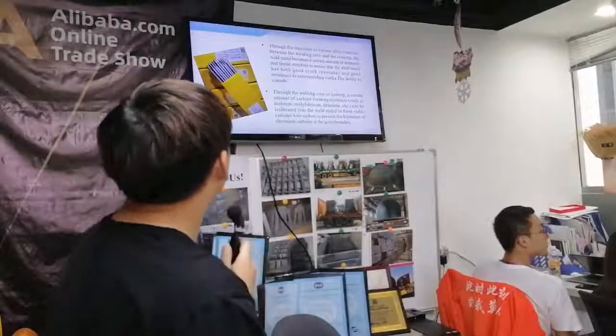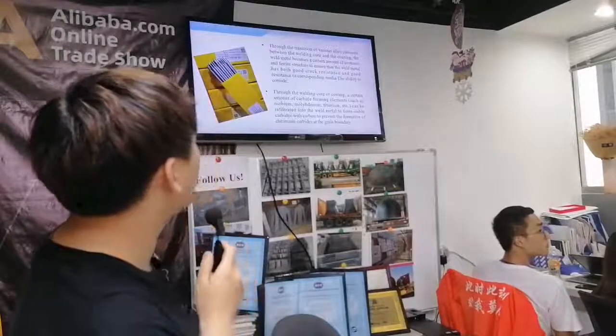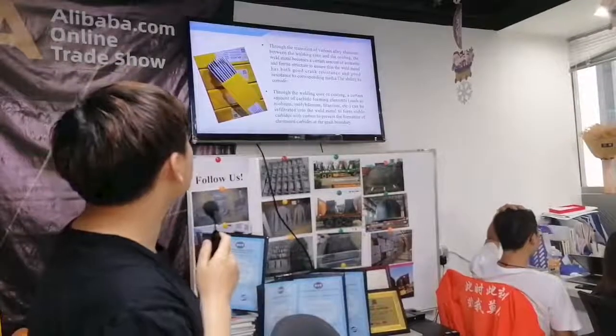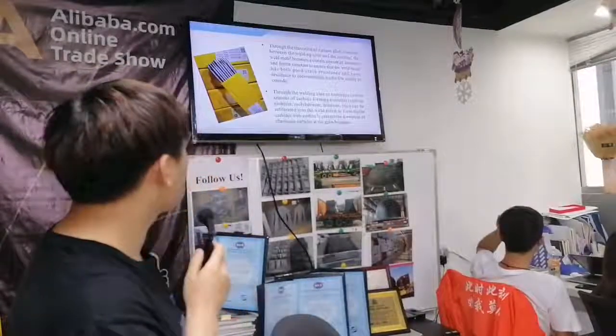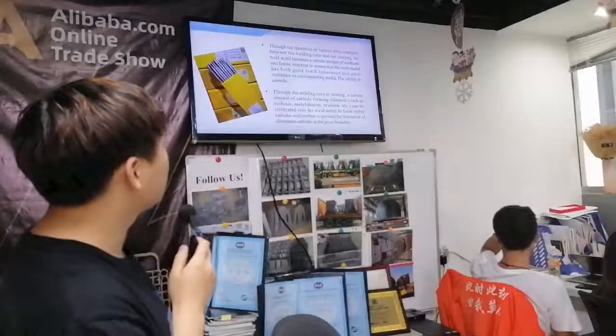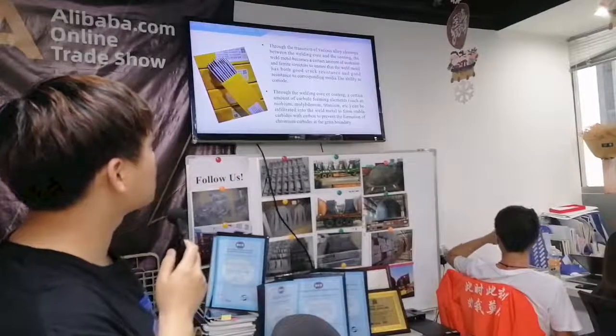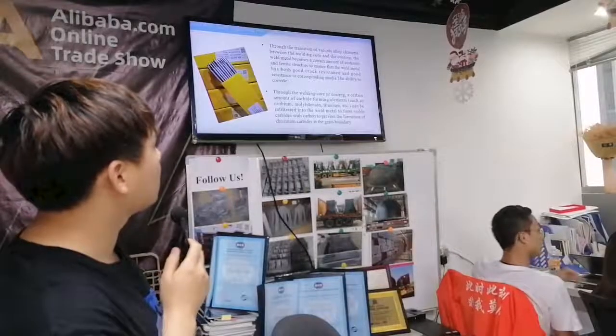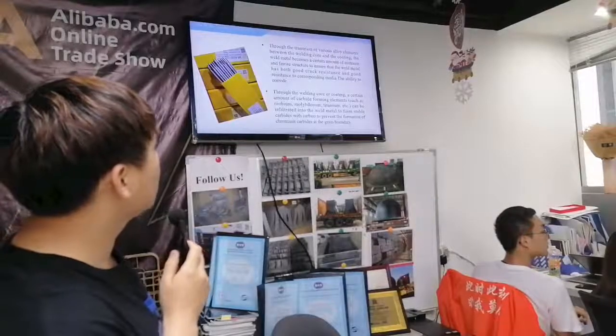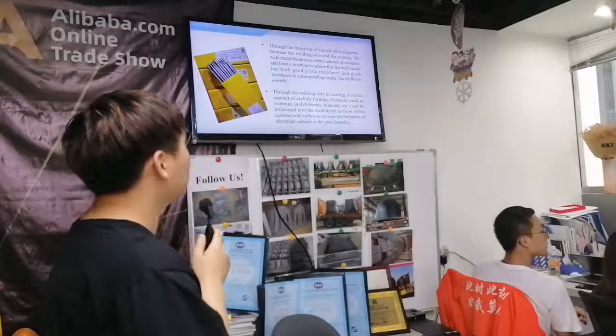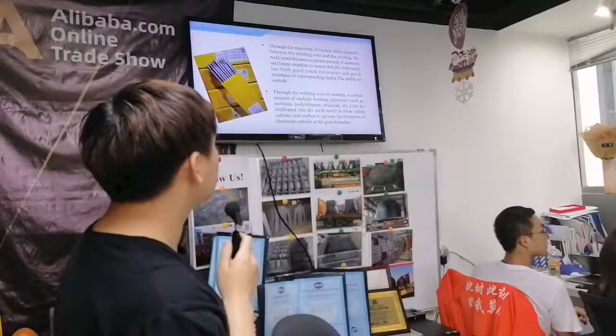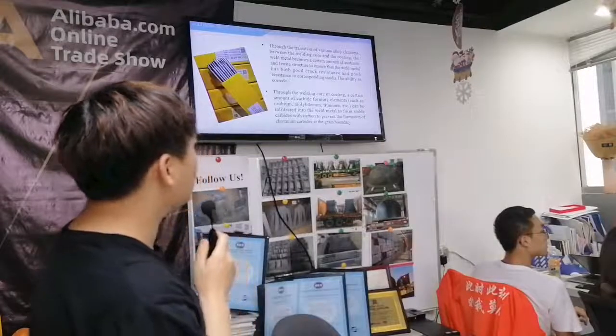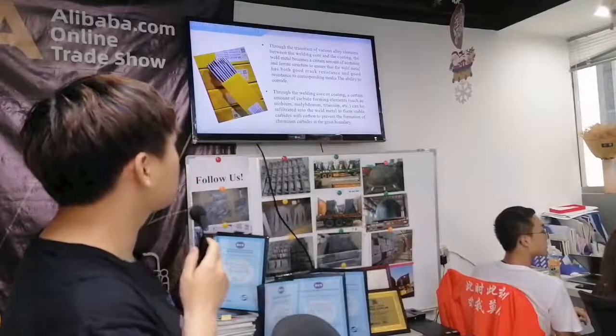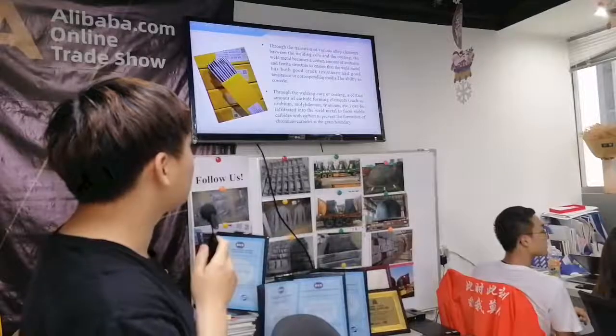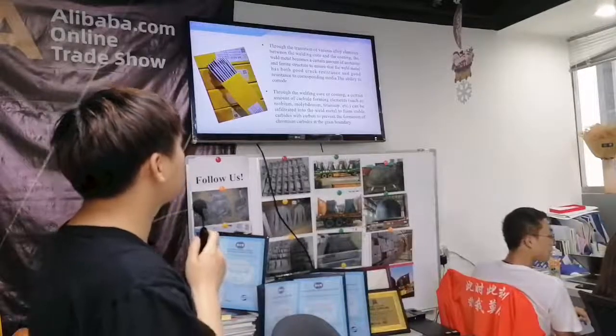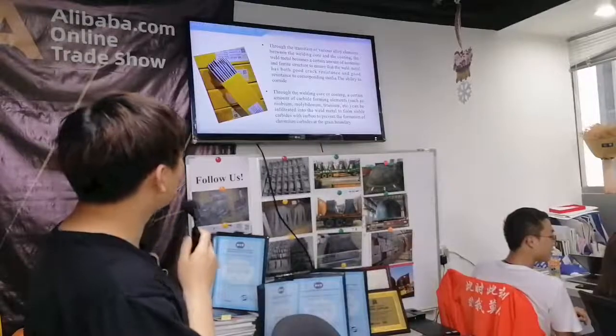And then I will introduce the performance requirements of the stainless steel electrode. The transition of various alloy elements between the welding core and the coating makes the weld metal become a certain amount of austenite and ferrite structure, to ensure that the weld metal has both good crack resistance and good resistance to corresponding media corrosion.